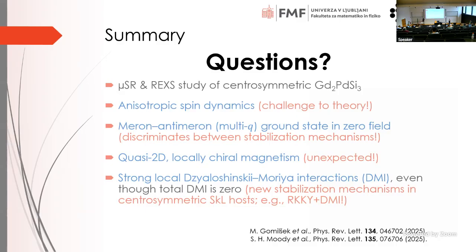Yeah, so this is in the category of speculation, basically. It's not been calculated by DFT. We're trying to do that now, actually. So that's the plan, to calculate this from first principles. But in principle, DMI is supposed to always be the first perturbation that you have to any kind of isotropic thing, as long as it's allowed, as long as there's some local chirality. But previously, people neglected this effect because globally, the whole unit cell is achiral. But actually, it matters what is within one layer because the layers don't talk enough. So locally, there are DMI interactions that are allowed, so expected to be strong because of that.